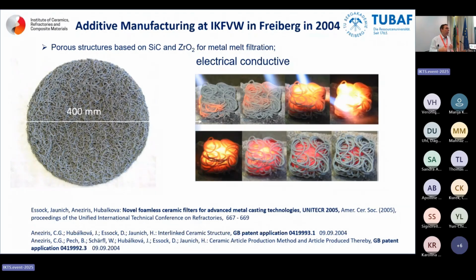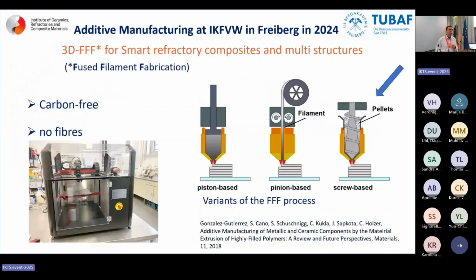Of course, you can do it also with zirconia, but keep in mind, silicon carbide is an electric conductive material, semiconductor, as well as at elevated temperatures. Also, zirconia above 1000 degrees Celsius, it becomes electric conductive. Yes, we have also the oxygen and all these kind of issues, but these are functional materials. We can activate them. And keep in mind, aluminum oxide, above 1000 degrees Celsius, you have 10 power to 4 higher electrical conductivity. So these are issues in order to meet the demands for going to smart refractories, as Hong Peng yesterday mentioned.